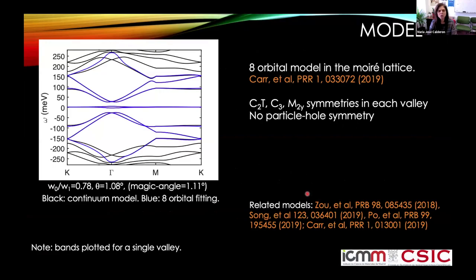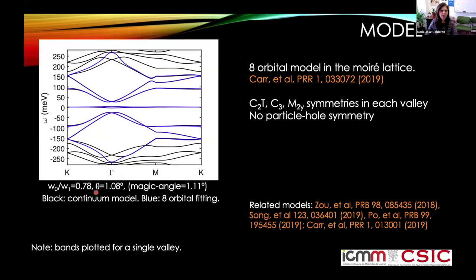Due to the topology of the flat bands, we cannot build a model for only the flat bands with the correct Wannier states, so we need to include the remote bands as well. We have chosen a particular proposal by current collaborators using an eight-orbital model for the moiré lattice. This allows us to keep all the important symmetries of the system: C2T, C3, and mirror symmetry. We chose a rotation angle of 1.08°, very close to the magic angle of 1.11°, and the blue lines show the fitting with this eight-orbital model against the continuum model in black.